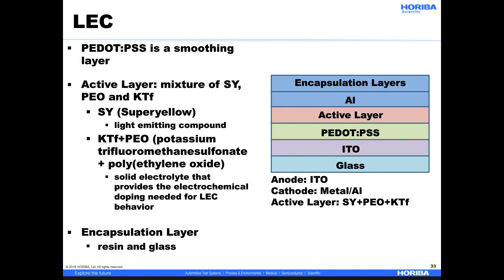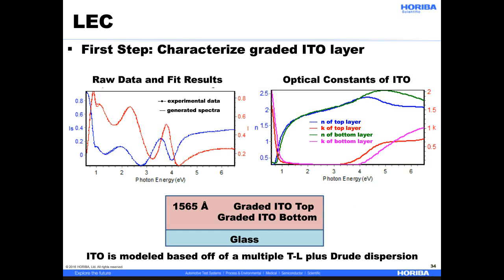Just like we did in the other examples, we'll characterize this step by step. The first step here would be to characterize the graded ITO layer, so again we have index grading. You can see on the right the optical constants of the top and the bottom of the ITO. This ITO is around 1565 angstroms thickness from ellipsometry, and on the left you have the raw data and the fit results.